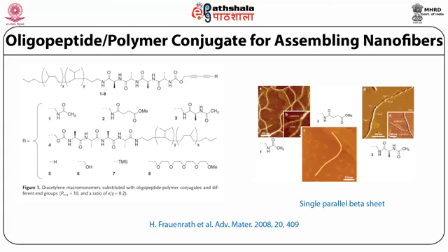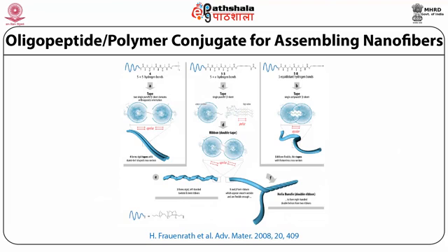The AFM image shows that compounds 1, 2 and 3 form very long fibers with high aspect ratio, and these fibers have parallel beta sheet domains with very pronounced twisting in the fiber. But for compound 4, no twist was observed and only flat tapes were observed, which comes from a single parallel beta sheet unit. These different molecules can be categorized into 3 different classes.